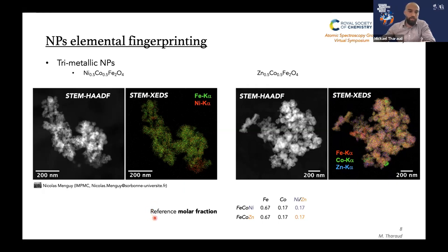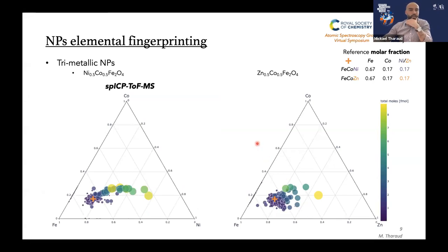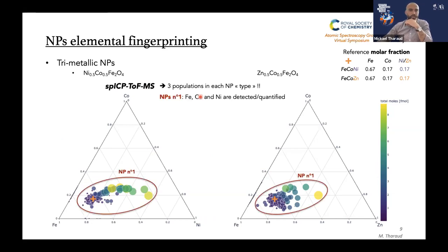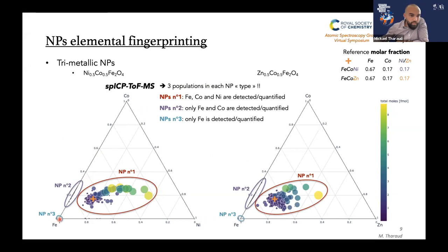However, we took the reference molar fraction given by the manufacturer, and you can see here that there is almost 67% of iron, 17% of cobalt, and almost 17% of nickel or zinc, depending on the type of nanoparticle. So we decided to analyze those nanoparticles using single particle ICP TOF-MS. Here I plotted the ternary diagram of the number of moles of cobalt versus iron, and on the right corner, nickel or zinc. By doing this kind of analysis, it was quite surprising that three different populations show up: a first one with iron, cobalt, and nickel, a second one with only iron and cobalt, and a third one, maybe you can't see it, it's over there, with only iron detected.